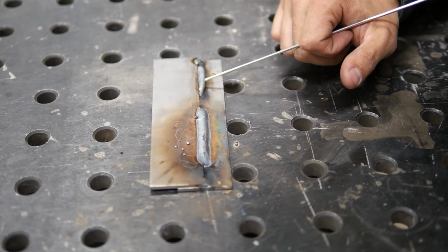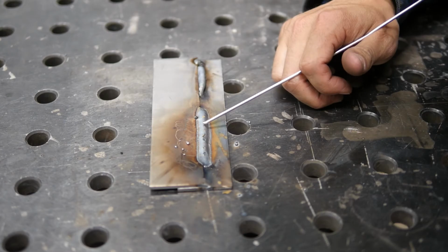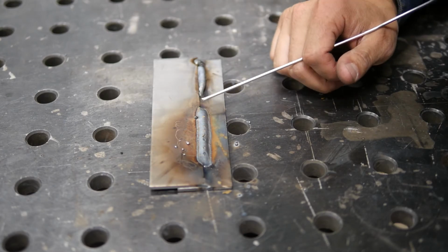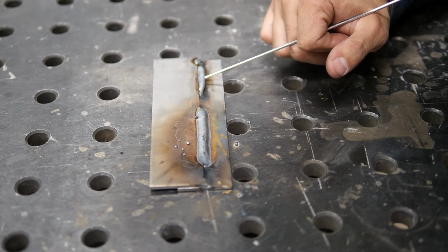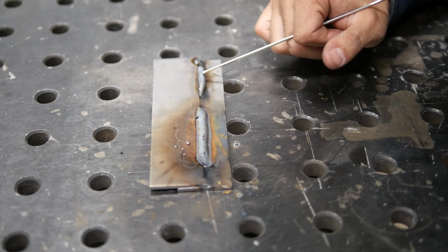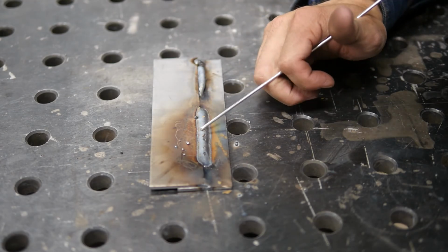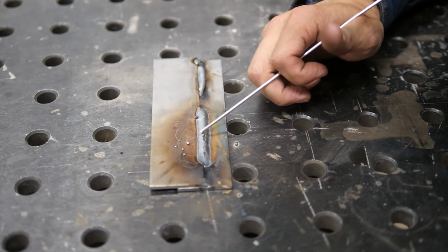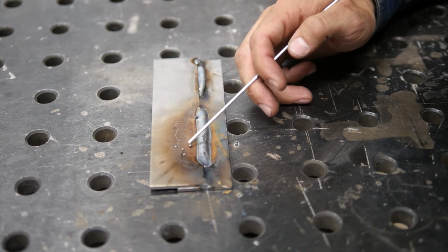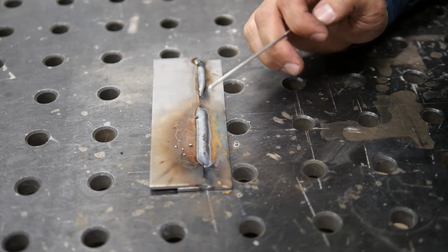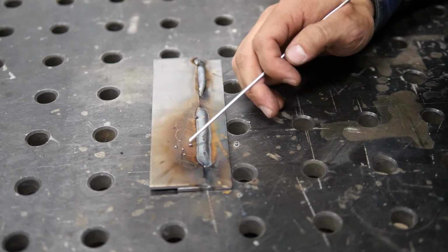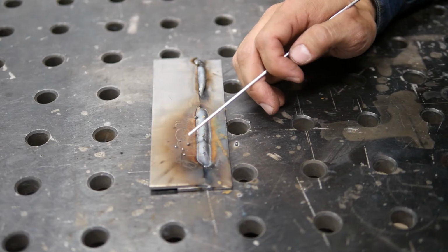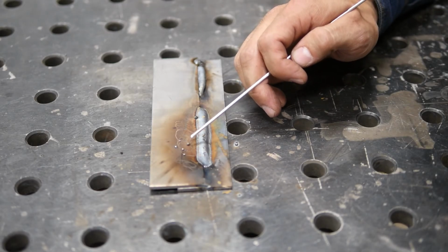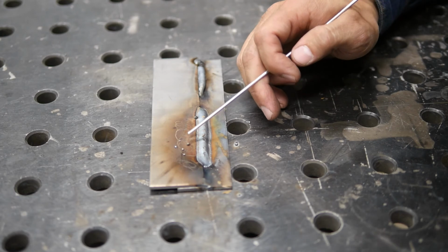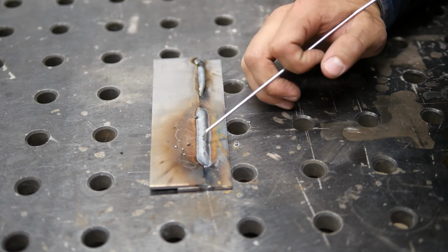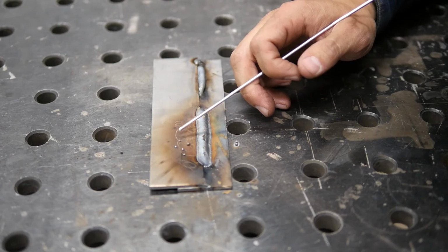All right, 10 volts and 24 volts. Now, there's pluses and minuses of both welds. Well, actually, there's no pluses to the too low voltage. That weld's horrible and that won't stand the test of time. But the higher voltage weld, there's only a few little problems with this one. First off, we'll talk about the spatter. And that's the pieces of the wire that didn't quite make it into the weld and got thrown out of the way. This happens because our arc length is really, really long. So the pieces of wire have to travel a really long way through the arc, and sometimes they just get shot out of the side.